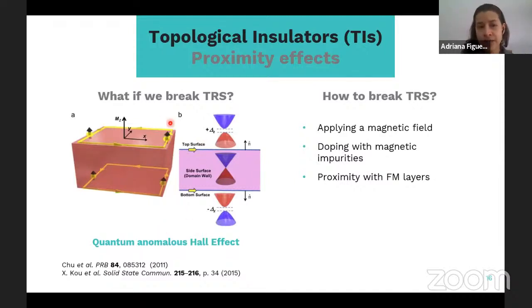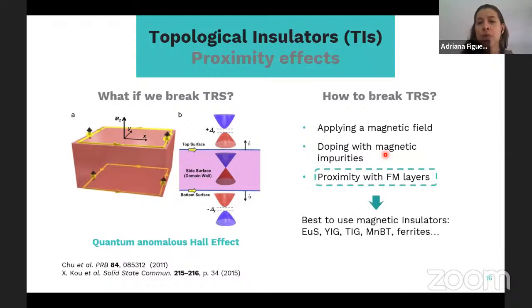And also it's interesting to introduce this magnetic order in the TI, because those topologically protected surface states become spin polarized, and those can be even more attractive for spintronic applications. So we want to break time reversal symmetry, and we can do so by either applying a strong magnetic field, or by doping with magnetic impurities, or by proximity with ferromagnetic layers, which is what I'm going to tell you about, because we use magnetic insulators since we don't want those surface states to be affected by the metallic character of a metallic layer.